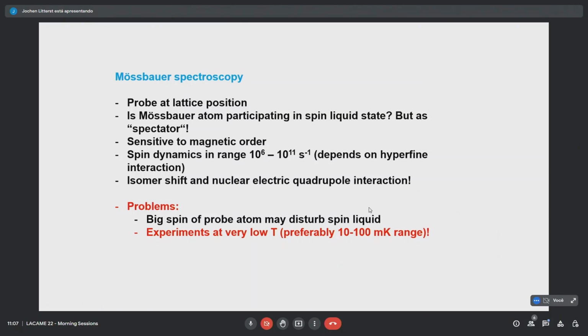There, for sure, we are also sensitive to the magnetic order. Here we are sensitive to spin dynamics, which is similar to muon spin rotation, but it depends strongly which hyperfine interaction you are looking at. For sure, we have here isomer shift and also quadrupolar interaction, which doesn't exist in the muon case. The big problem we face here is that if we introduce an extra Mössbauer atom, it may severely disturb the spin liquid in its surroundings. One has to think about that.